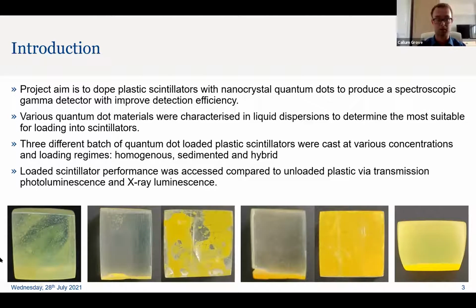So the 3 batches, if you can see at the bottom, we have a homogeneous batch, a sedimented batch, and then a hybrid batch that has a sedimented layer of highly concentrated quantum dots at the bottom and a homogeneous layer similar to the first batch. And so I'm going to be talking through briefly the casting process and then the early results that came out of it, specifically with respect to X-ray luminescence.